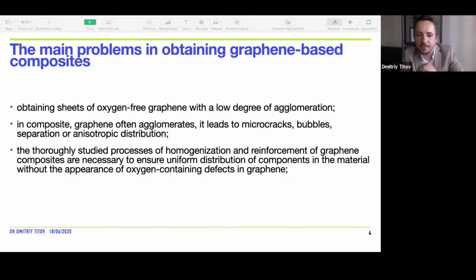The main problem is obtaining oxygen-free graphene sheets with low degree of agglomeration. And in the composite, graphene often agglomerates. It leads to microcracks, bubbles, separations, and anisotropic distribution. So the thoroughly studied processes of homogenization and reinforcement of graphene composites are necessary to ensure uniform distribution of compounds in the material without the appearance of oxygen-containing defects in the graphene.